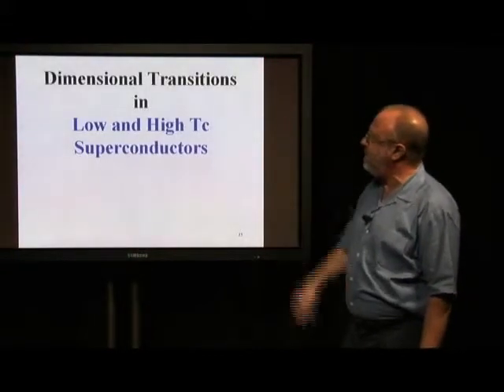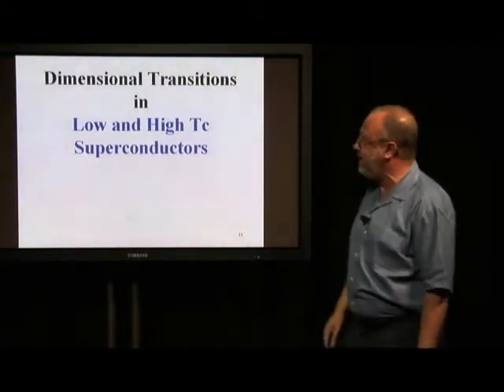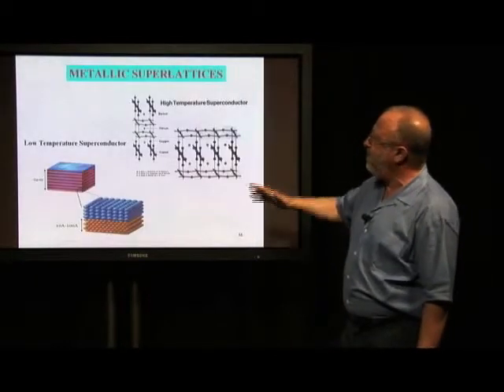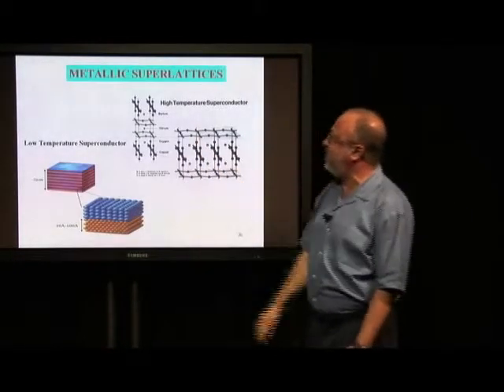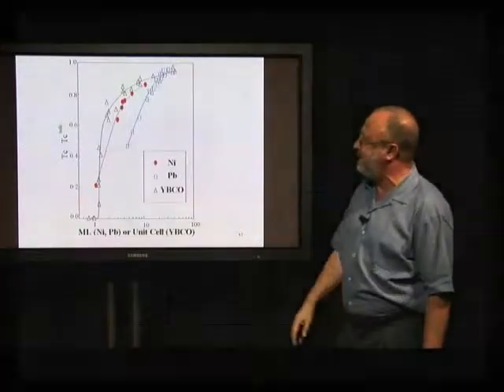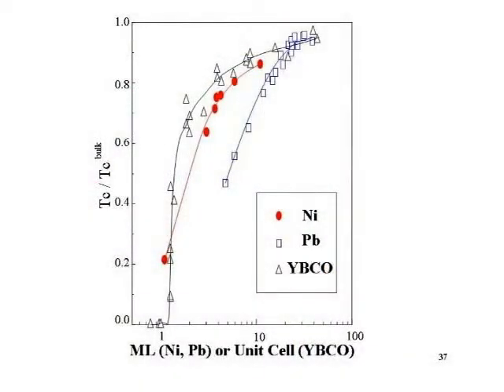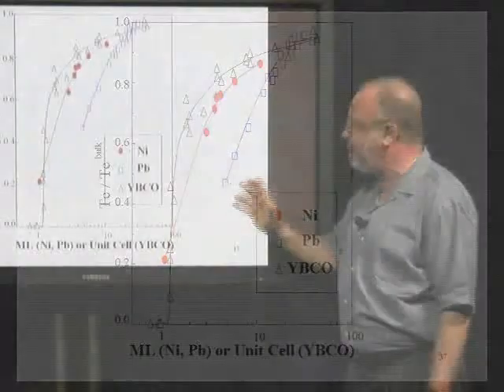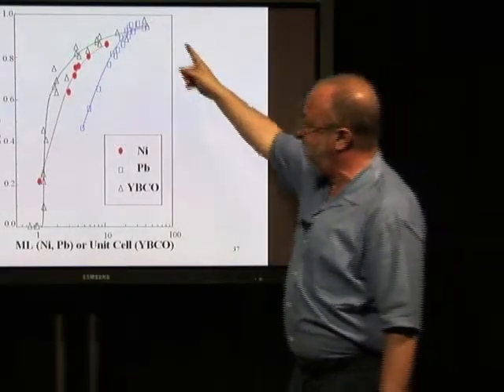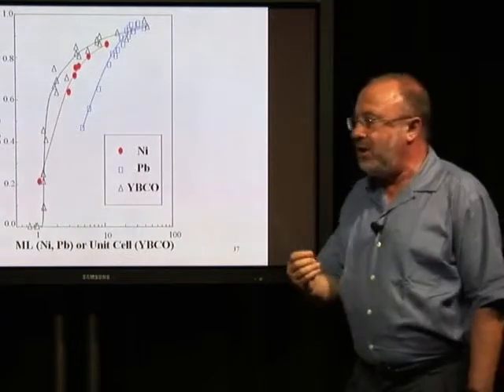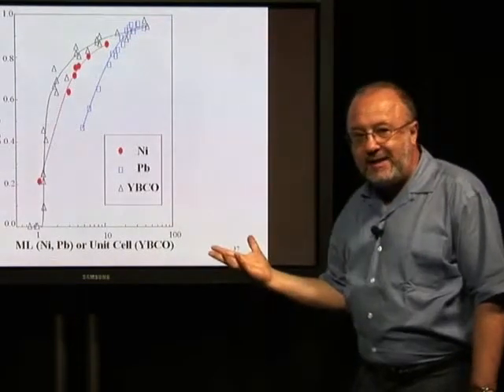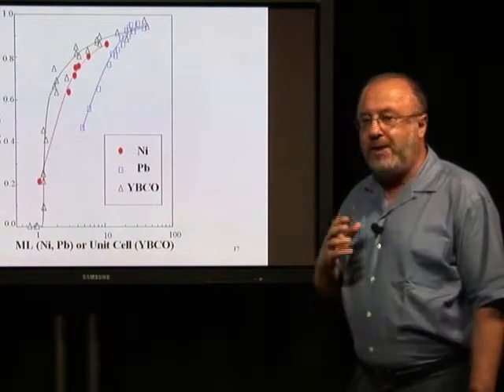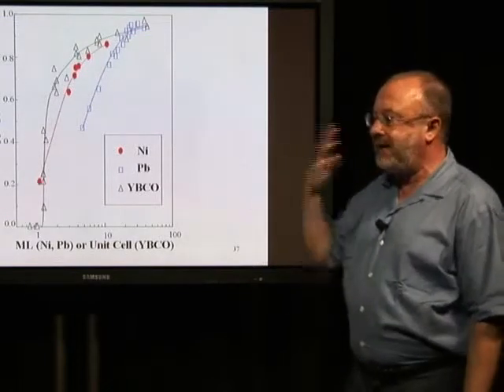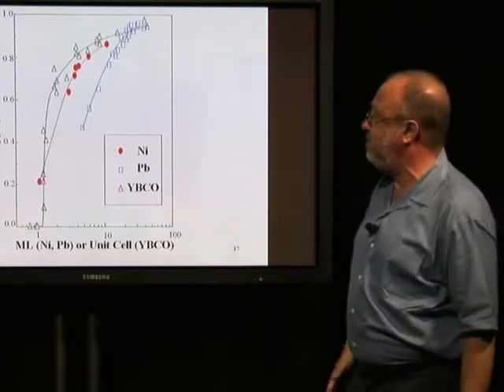Now I want to tell you about dimensional transition in low and high Tc superconductors. This started with some work in which we compared what happens in low temperature superconductors and in high temperature superconductors. Here is one study that we started, with the transition temperature as a function of thickness of these individual layers. As you make the layers thinner and thinner, the transition temperature decreases. It decreases either because of proximity with other things around, or because there is a dimensional change, as the material goes from being three-dimensional to two-dimensional.